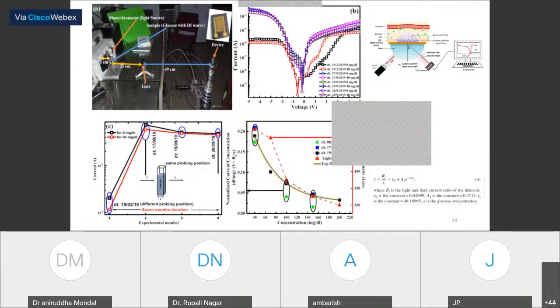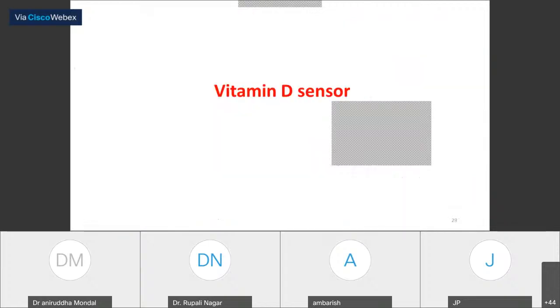We are trying to fabricate an enhanced photodetector which can be used to directly measure the blood sugar of the human body without causing any pain from extracting blood. We have also developed some vitamin D sensors. Here we have used Ag nanoparticle-based titanium dioxide nanowire-based sensors. Everything is deposited by the glancing angle deposition technique.